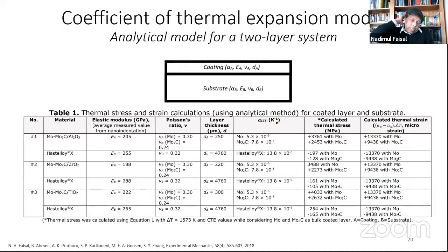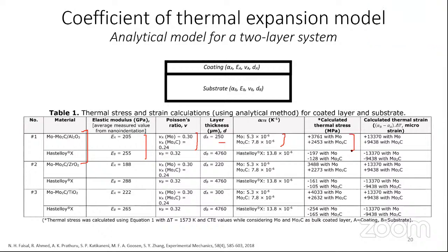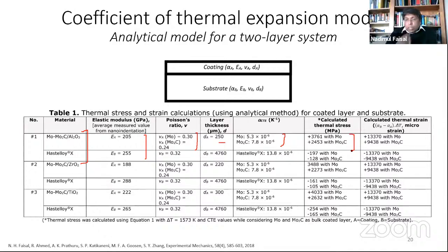So here we did some analysis on a multi-phase material. You can see it was a mix of molybdenum carbide with alumina on a Hastelloy substrate. Here we selected some properties, or measured some of the properties, with some data coming from literature, Poisson ratio, and the thickness was the final thickness. And we selected the coefficient using literature values. For some materials you may not find the property, so you can come up with a property which is as close as possible. So you calculate the thermal stress, and you can see these values are very high in megapascal. Later on, I'll show you that the experimental values will be about 10 times lower than these.